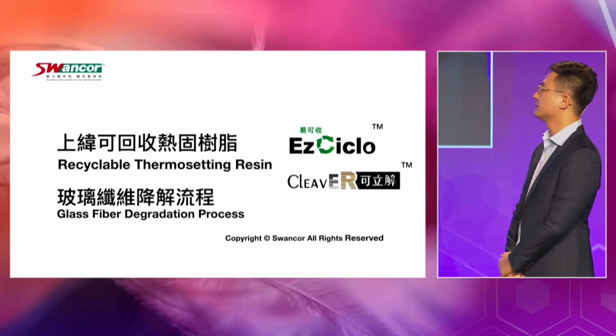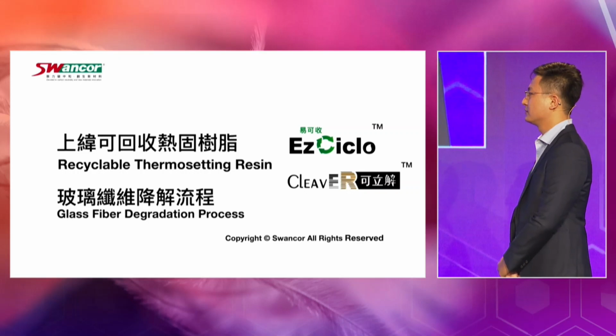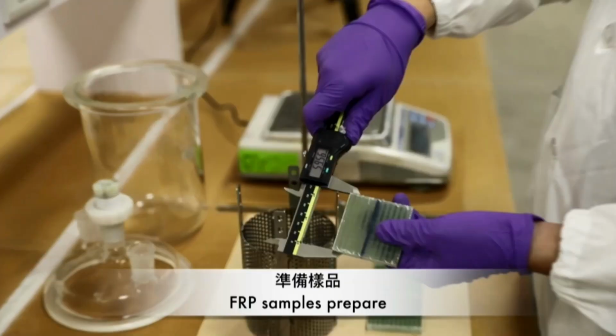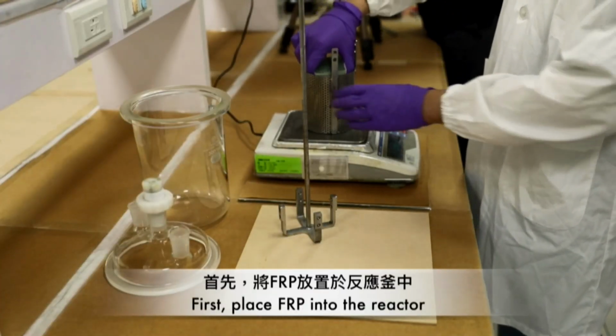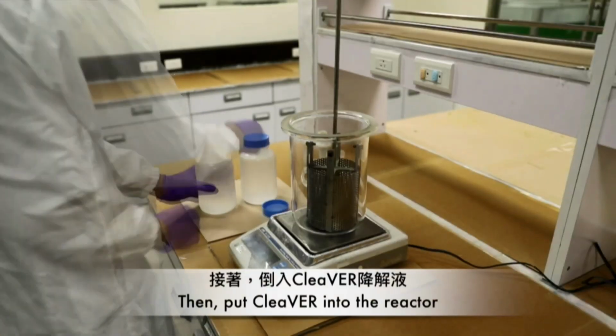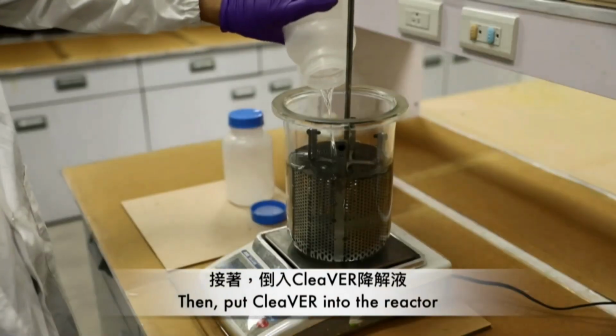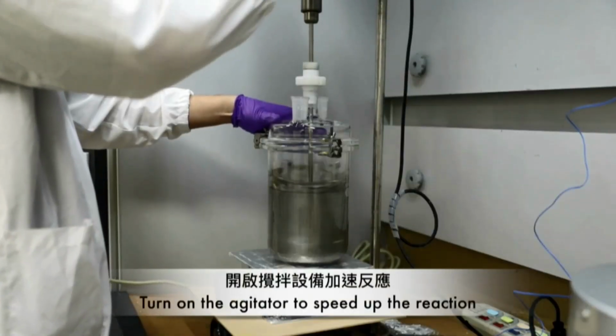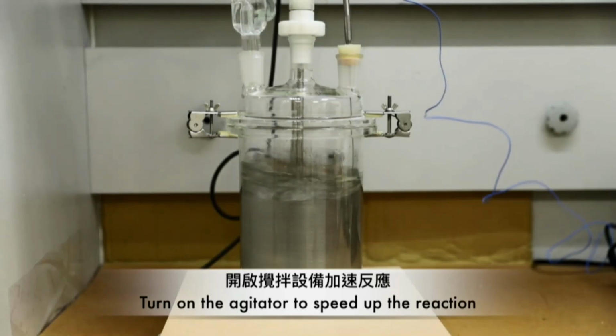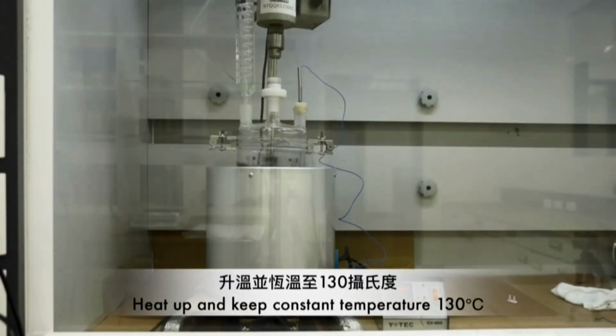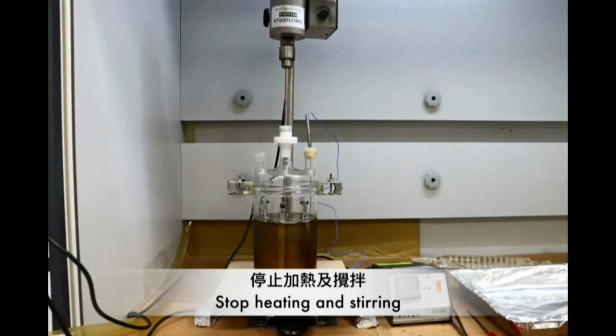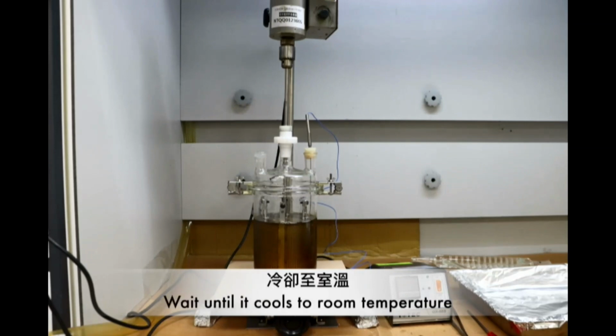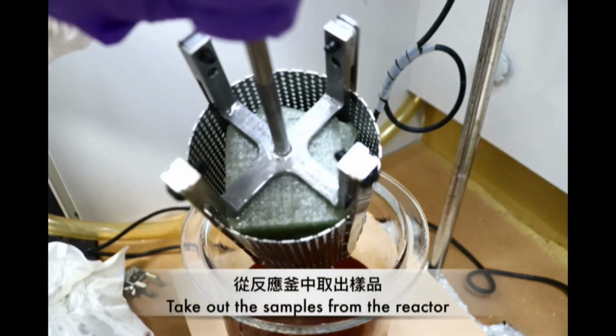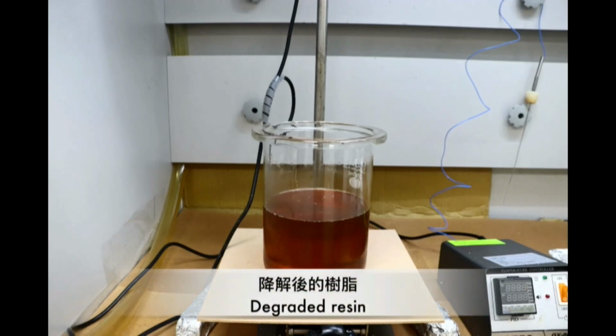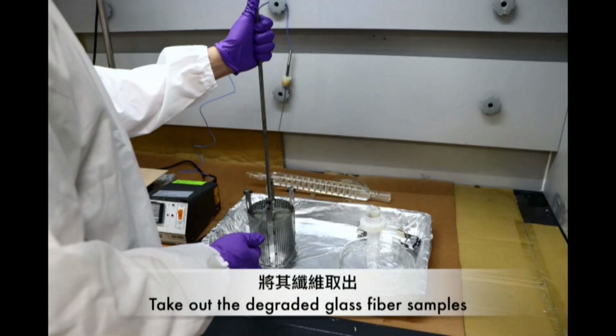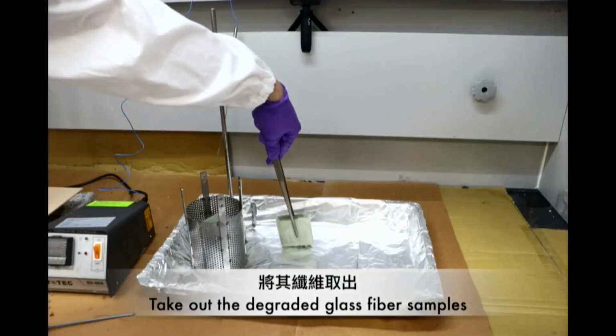Swancor recyclable thermosetting resin EzCiclo and CleaVER glass fiber degradation process. Prepare the FRP samples. First, place FRP into the reactor. Then, put the degradation material CleaVER into the reactor. Turn on the agitator to speed up the degradation reaction. Heat up and keep a constant temperature at 130 degrees Celsius. Heating continuously for 3 hours. Stop heating and stirring. Wait until it cools to room temperature. After the degradation process, take out the samples from the reactor. This is the degraded resin. Then, take out the degraded glass fiber samples. You can find the fibers effectively swelled during the degradation process.